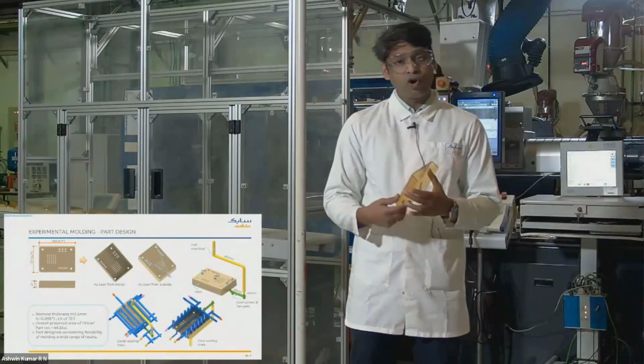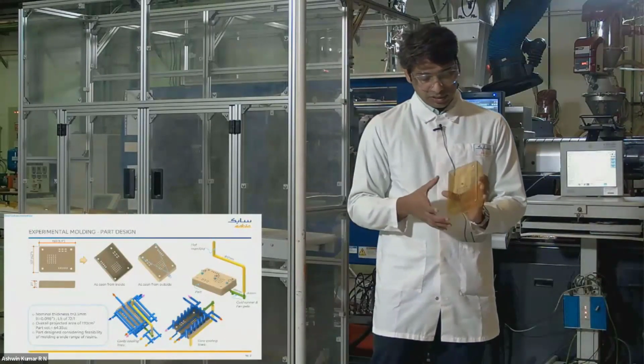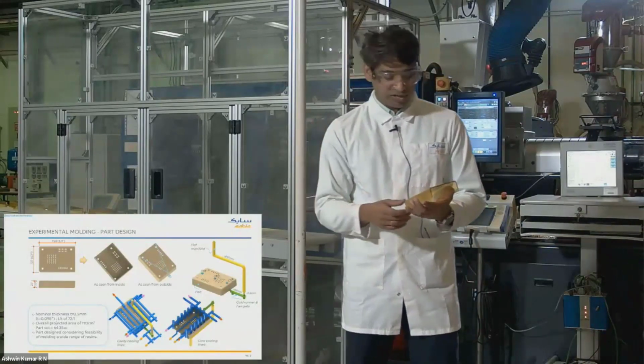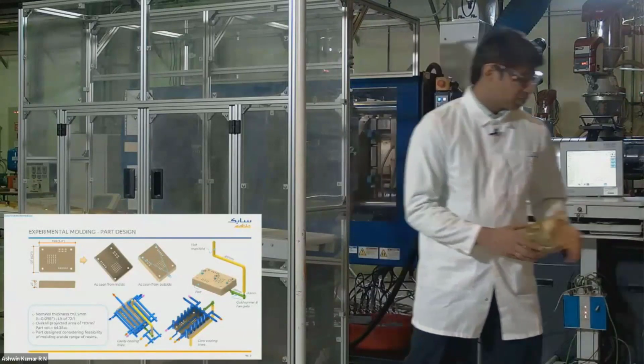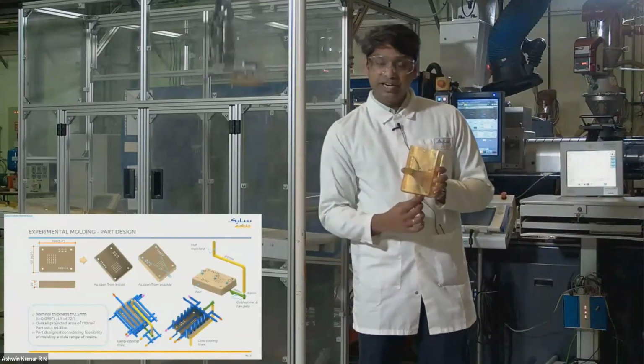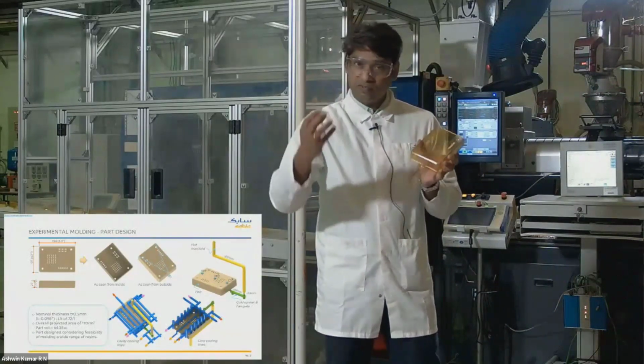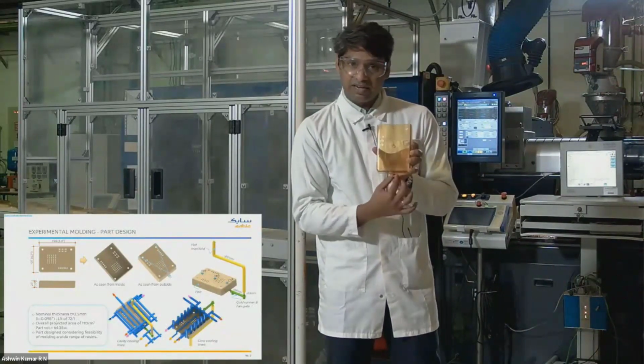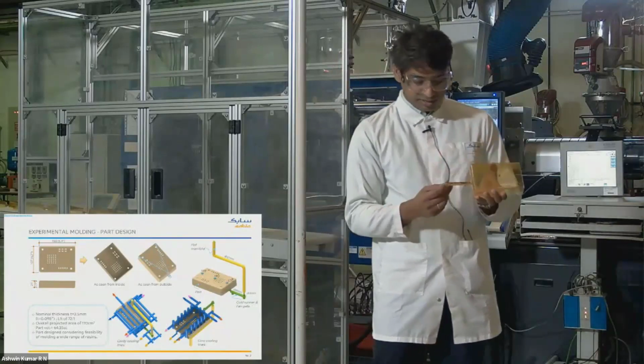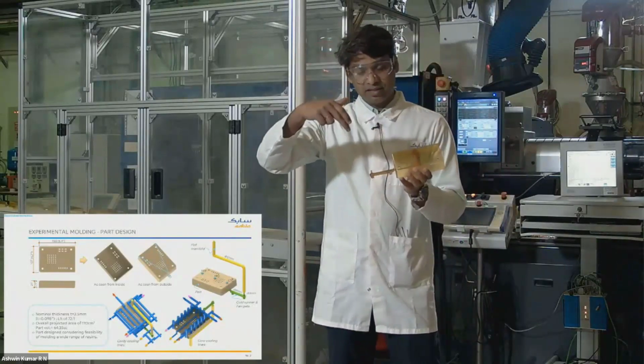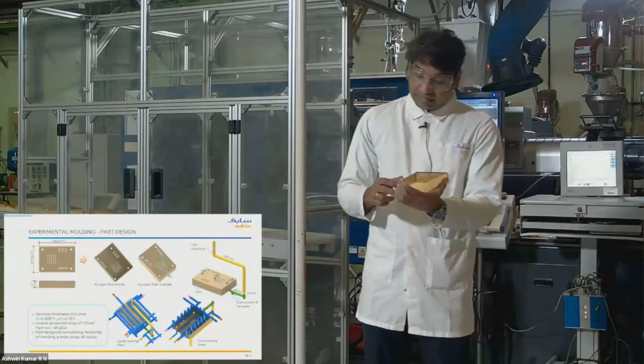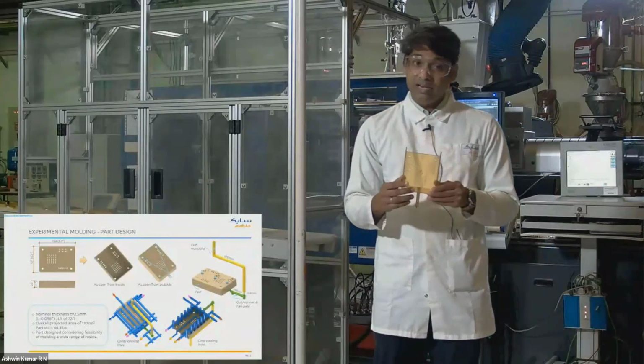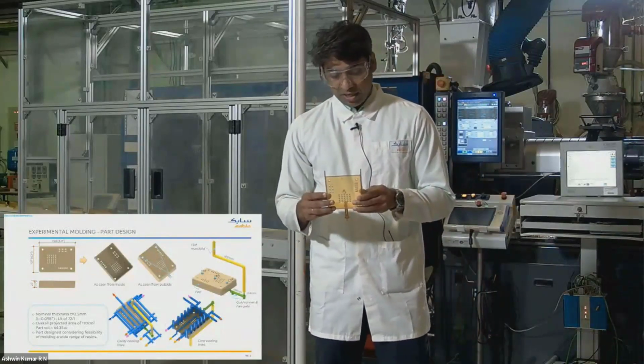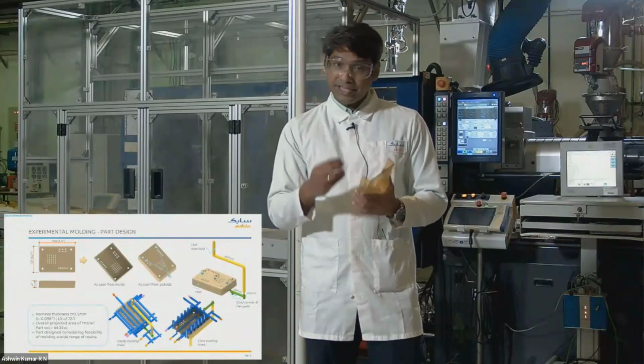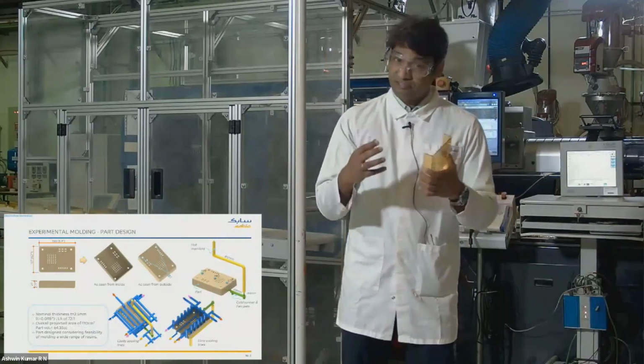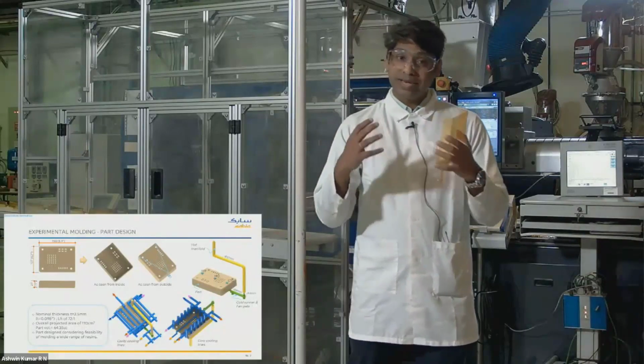And this is about a uniform 2.5 mm thick part with about 220 by 160 length. And to mold this part, we are using an edge gate scenario here, which is basically a combination of hot and cold runner. And you see we have a decent edge gate with a trapezoidal shape of runner with a small cold sprue, which is fed by the hot runner, right? And another important thing I want to highlight while we are developing the tool for this design, we have given a lot of emphasis to make sure that the part forming surfaces in the tool are maintained at a very constant temperature, right?